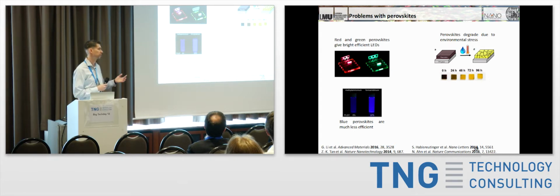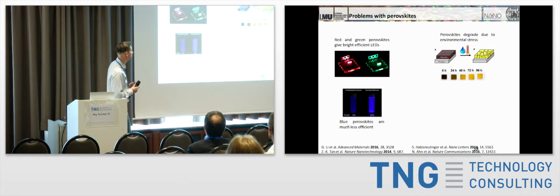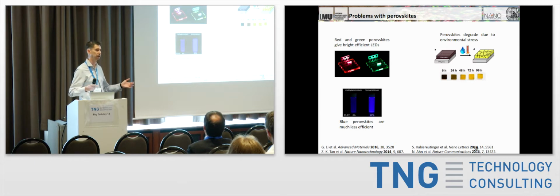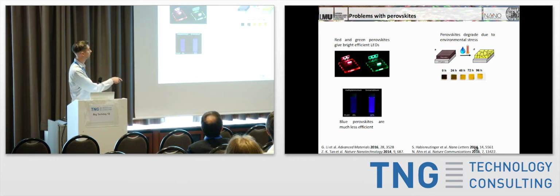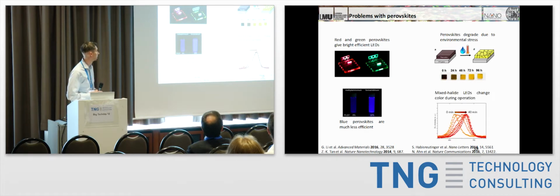So I told you about the first solar cell that was built into an aqueous environment and disintegrated within about 30 seconds. That's also a big problem for solar cells, because if you have a solar cell sitting anywhere, it's going to heat up, it's going to cool, it's going to expand, it's going to contract, and that then is perfect for letting water in, and that lets then solar cells degrade quite quickly. You can see here the nice black absorber, meaning essentially all the light is absorbed. Relatively quickly, it becomes more and more yellow as this perovskite disintegrates back down to one of the original components, the lead iodide. So that's one of the big problems that people are then looking into encapsulation.